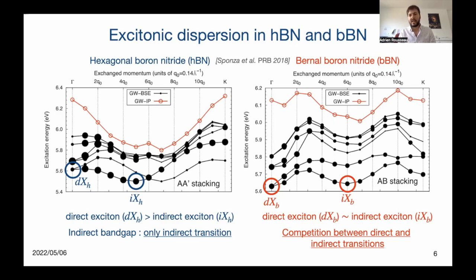For the Bernal boron nitride, the excitonic dispersion shows two minima, which lie at almost the same energy for the indirect exciton and the direct exciton. And only the experiments could allow us to discriminate and conclude on the nature of the bandgap for Bernal boron nitride.